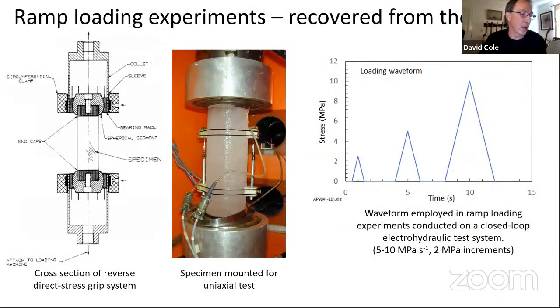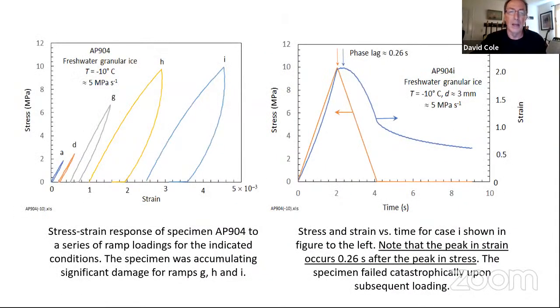All right, so now I'm going to briefly talk about our experiments and these ramp loading experiments. In laboratory tests, we've had this methodology around for a long time, but basically it's uniaxial compression, although the samples are clamped in a way that we could do reverse direct alternating tension and compression with this. We've applied a series of ramps, as I discussed before. And we saw this one earlier, but now we understand that as we're damaging the ice, we're in fact increasing the dislocation density. And we have this fairly substantial delayed strain that comes out after the unloading has started.